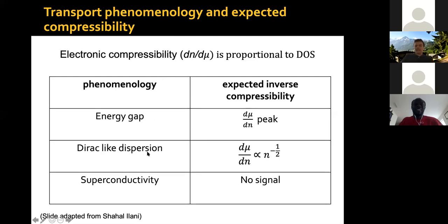A Dirac-like dispersion out of charge neutrality, Dirac bands, will lead to an inverse compressibility signal which goes as 1 over square root of density. So it's a decrease with a specific shape, a decrease of your inverse compressibility.